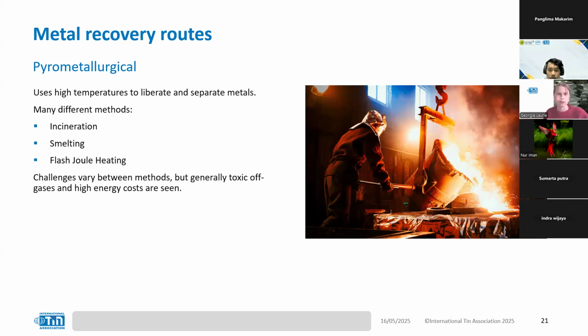Flash Joule heating, on the other hand, is emerging as a technique pioneered in recent research by researchers at Rice University in the United States. In this process, a high voltage electric discharge through shredded e-waste powder raises its temperature by about 3,400 kelvins within milliseconds. Essentially, the material is flashed into an extremely hot state momentarily.